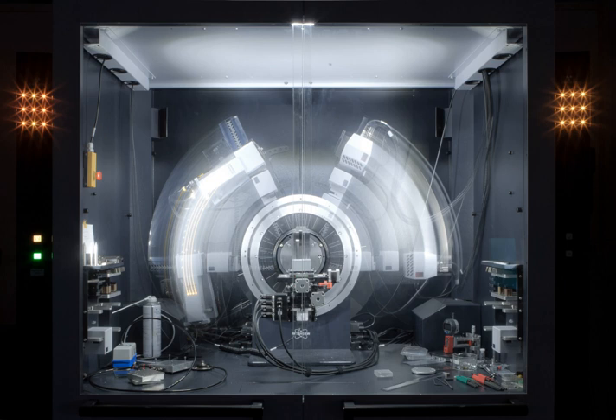The Laue back reflection mode records X-rays scattered backwards from a broad spectrum source. This is useful if the sample is too thick for X-rays to transmit through it. The diffracting planes in the crystal are determined by knowing that the normal to the diffracting plane bisects the angle between the incident beam and the diffracted beam. A Greninger chart can be used to interpret the back reflection Laue photograph.